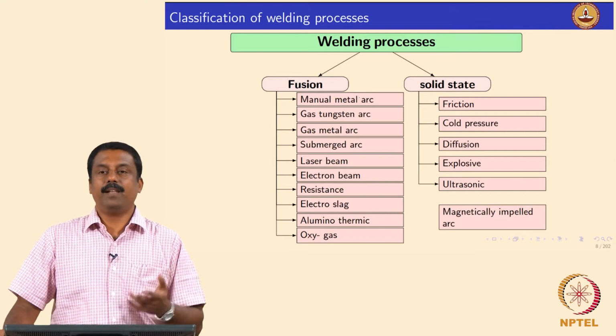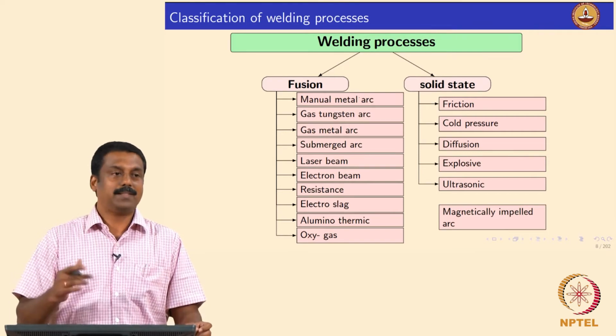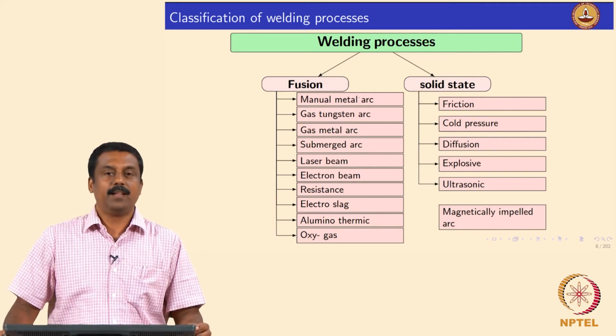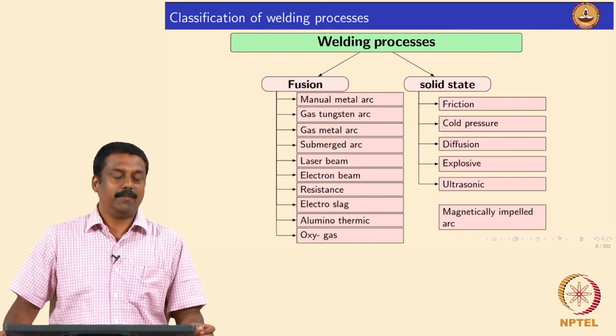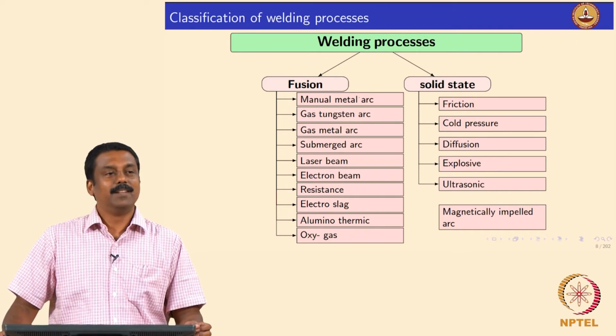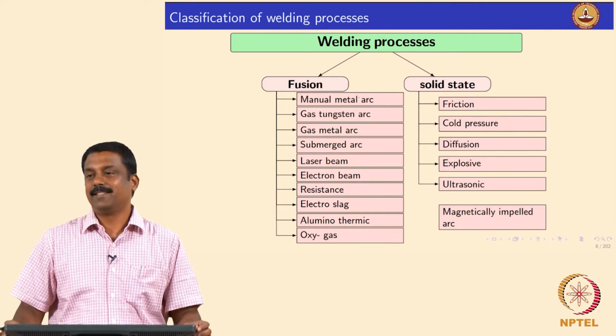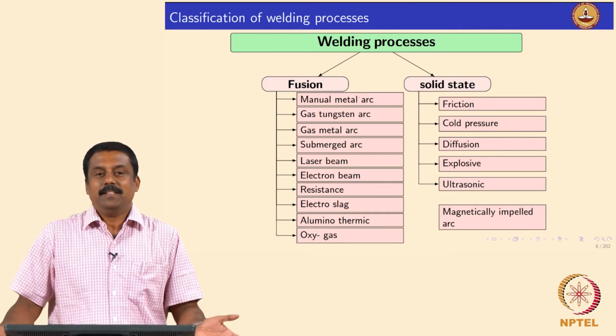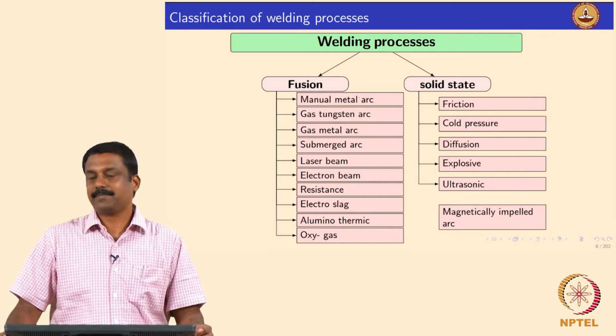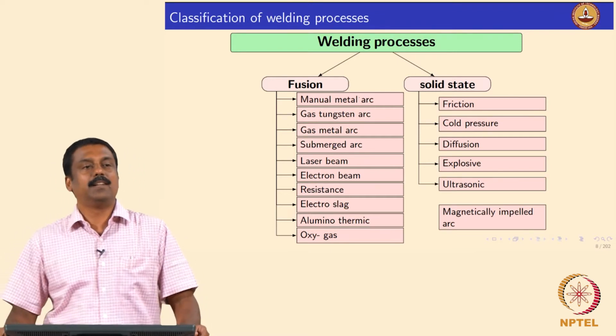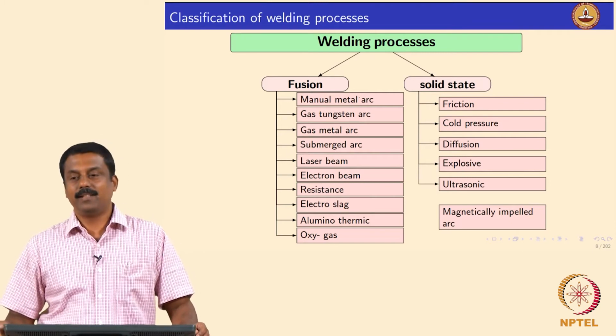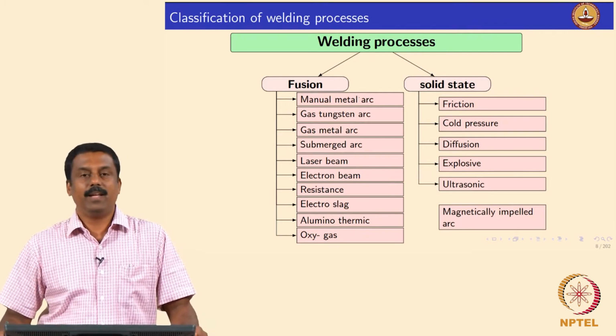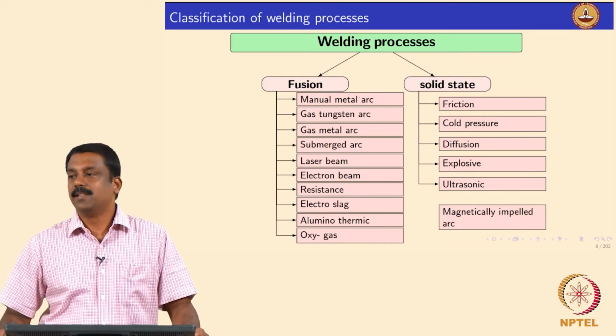And we also have nowadays a new process invented, and we are going to install it in 2 to 3 months in our lab as well. That is magnetically impelled arc butt welding, where we have arc and the pressure. It is very difficult to define which is rate controlling in this process, whether arc or pressure is rate controlling. So, we left it hanging. In this diagram it is hanging because it uses both arc and the pressure, and we will come back to that when we look at it in detail. This process uses both arc and the pressure to make the interfaces coalesce, right.